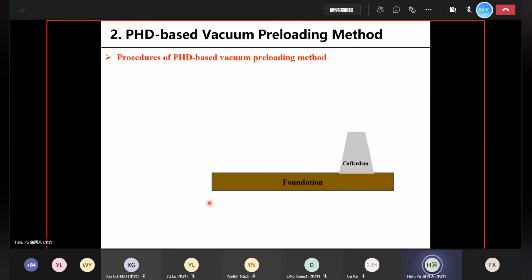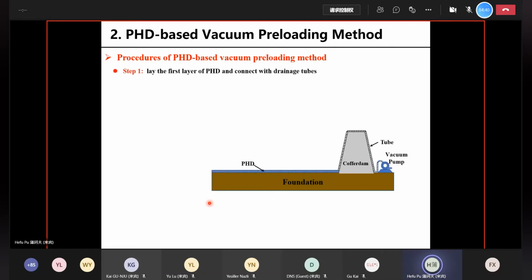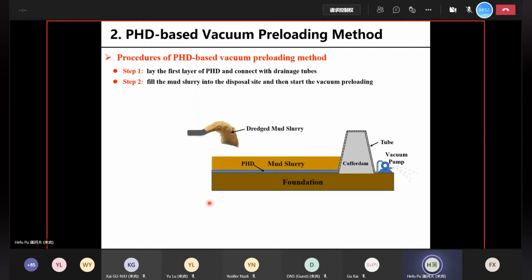First, let me show you the procedures of the PhD-based vacuum preloading method. First, we need to lay the first layer of PhD at the bottom of the disposal site and connect the PhD with drainage tubes and with vacuum pumps. And then we fill the mud slurry into the disposal site and then start the vacuum preloading to dewater the